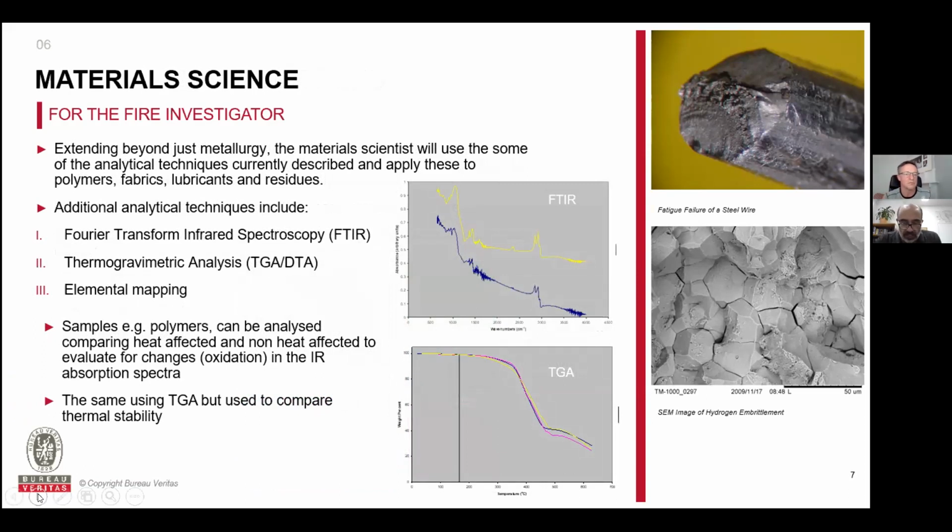But in addition to metallurgy, most of the team here are metallurgists, but we've also got our material scientists. So it extends beyond metallurgy, where the material scientists will use some of the analytical techniques that I've spoken about and apply those to things like polymers, fabrics, lubricants, residue, ceramics. A lot of techniques that we use quite extensively are FTIR and TGA, where samples of polymers, for instance, can be analysed comparing areas of heat effect and non-heat effect, looking for changes like oxidation in the spectra